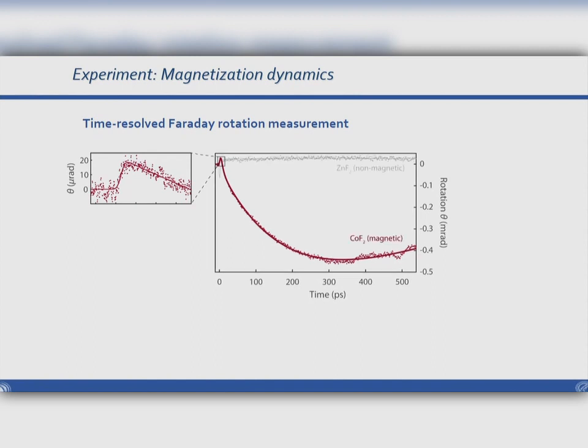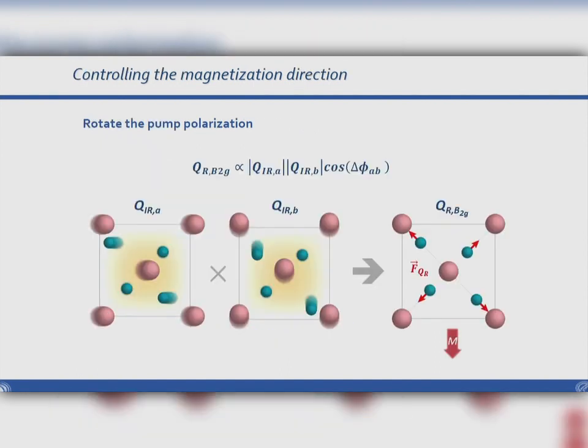If you do the same experiment with the zinc fluoride, which has exactly the same structure but is non-magnetic, you don't get this signal. So this makes us strongly believe that this is really a magnetic effect. And we also did an optical circular birefringence measurement that also confirmed that this is a purely magnetic signal. So antiferromagnetism is observed.